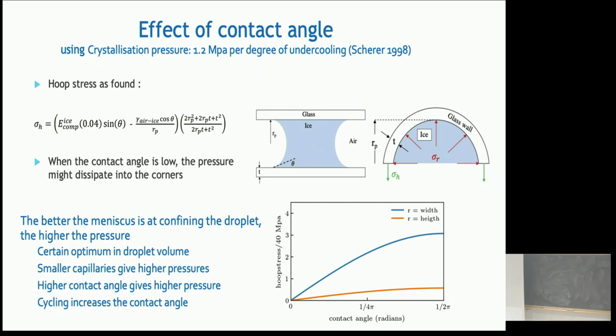That's also the reason why smaller capillaries break much easier than larger capillaries. And the cause of that is that there has to be a contact angle. If it's too flat on the surface, you won't exert any pressure on the wall, and the cycling increases the contact angle, and so increases the damage. As we saw, thanks for the question, it also increases the pressure.